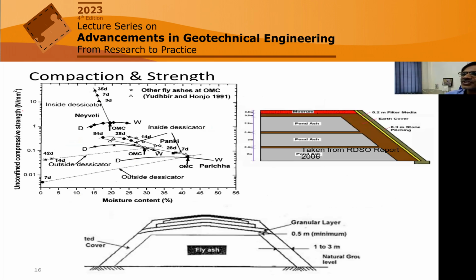Then look at the strengths. As I am compacting the soil, you see here, these points are with different moisture content. Instead of dry density here, it is plotted with the unconfined compressive strength. The variation is not much for a particular fly ash with the moisture content. But the same soil, if I put it outside the desiccator, the strength which was around 0.1, you see this is a log scale, 0.1 Newton per millimeter square, that means 100 kilopascal, has reduced to 0.04.